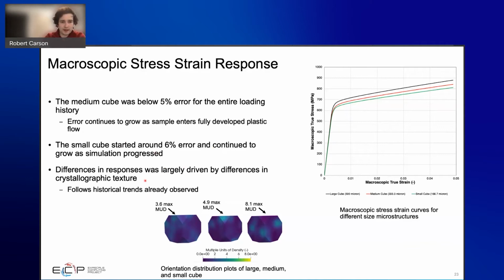And I will mention that the main difference between all of these responses was largely driven by the crystallographic texture between the materials. I'll get into a little bit later what crystallographic texture is, but you can think of it as a directional dependency on your material response. So it's quite important when you're modeling materials, especially when you're doing something that's not necessarily isotropic.